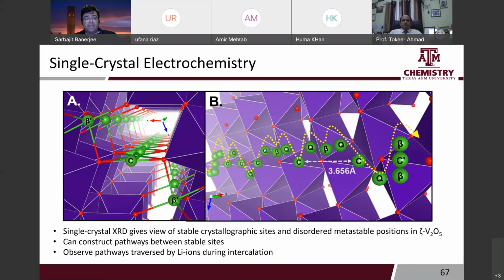We're starting with V2O5, lithiating it, and looking at the electron density maps, and saying, well, look, these are the regions where we can refine actual lithium sites, and here are diffuse regions with traces of electron density that we can start mapping. At room temperature, there's some occupancy of lithium there. It's not full occupancy, but we can say these are the pathways where, at room temperature, the ions are in the process of moving, right? So this allows us to map this, and you can increase the temperature and watch these change.